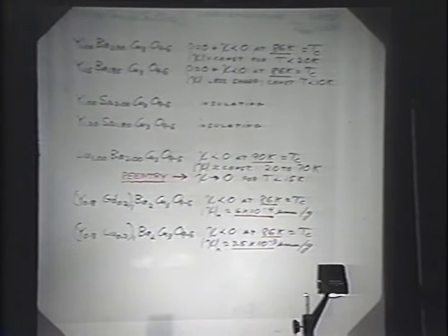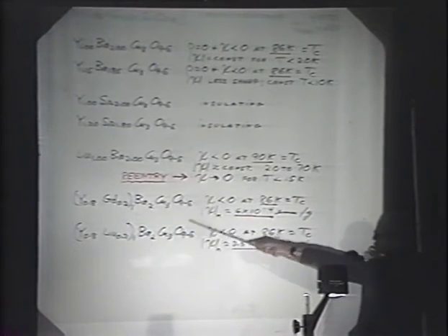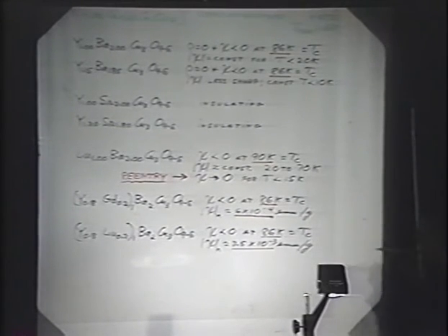We have a gallium diluted sample which has no effect upon the superconductivity temperature. However, the comparison between a gadolinium and a lutetium of the same concentration seems to show that the net plateau susceptibility is larger in the lutetium, meaning perhaps that the gadolinium is contributing a paramagnetic component to this superconducting susceptibility, but in no sense influencing the TC. So this would be, I think, similar to other data reported this evening.